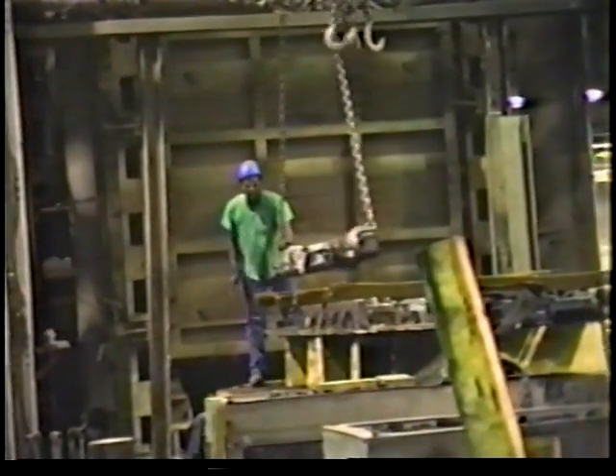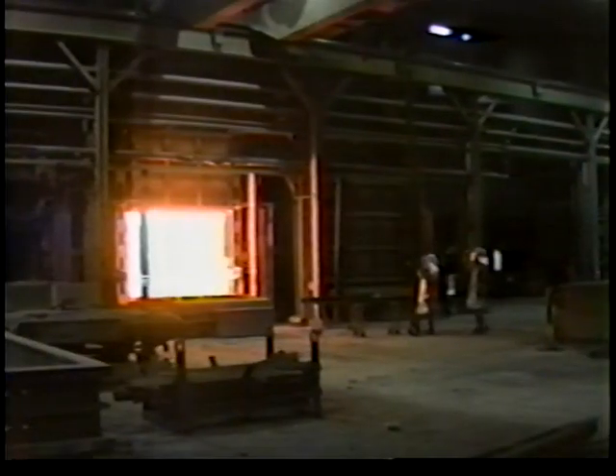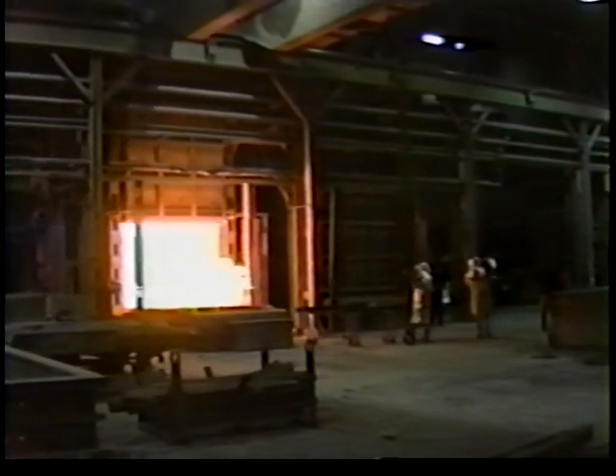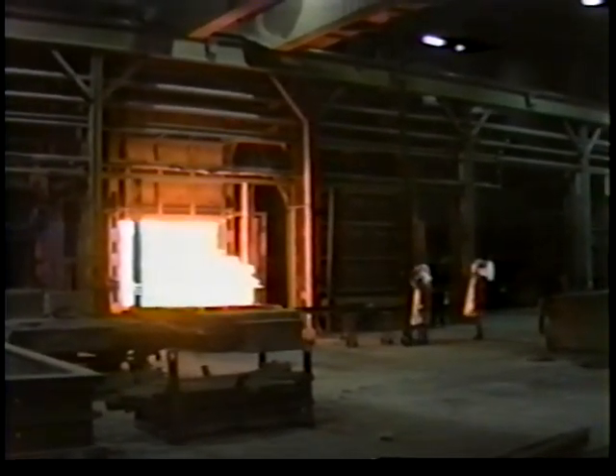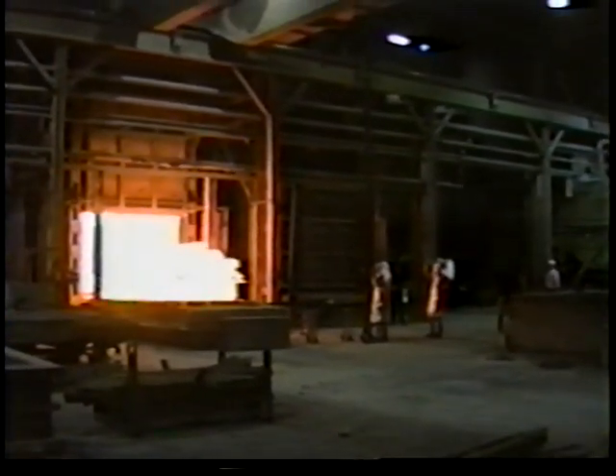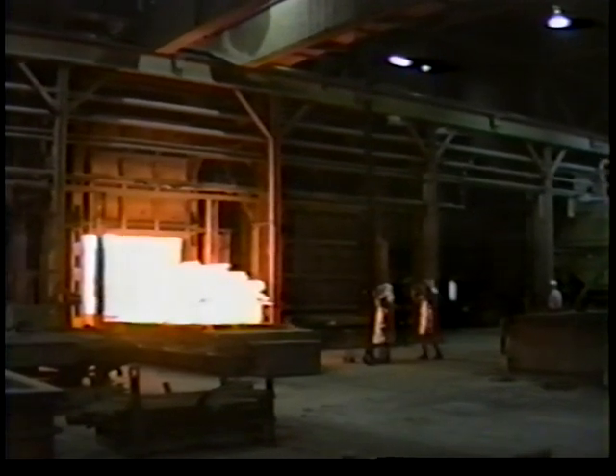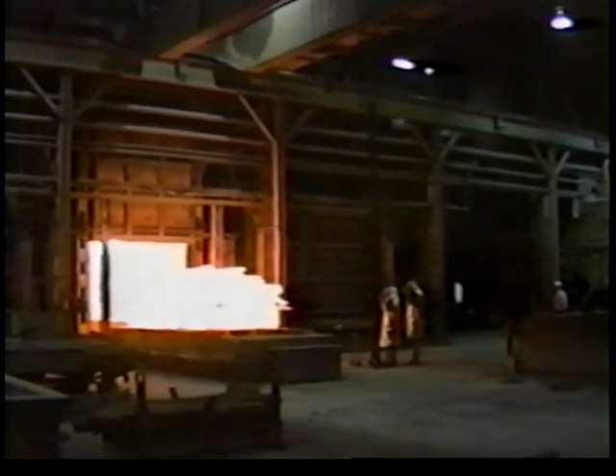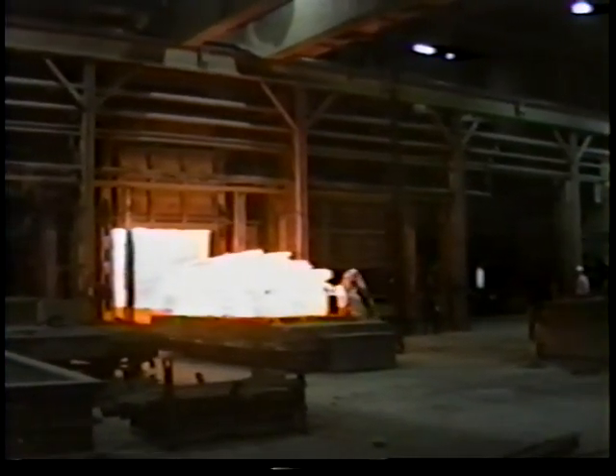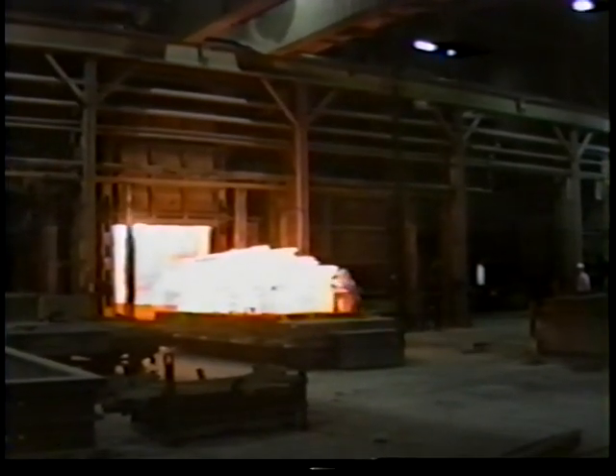When this load is completed, the car will be run back in the furnace and the heat treat cycle for manganese steel will be performed, which is to hold the castings at 1950 degrees for about 4 hours, followed by water quenching. You're watching the quench operation. From the time the furnace door starts up until the castings are underwater is held to 2 minutes or less. This rapid quench is what gives the unique properties to manganese steel of toughness and high wear resistance.